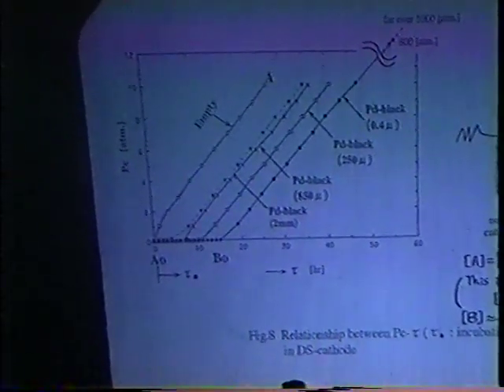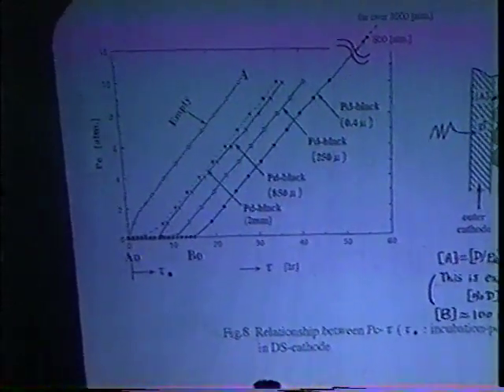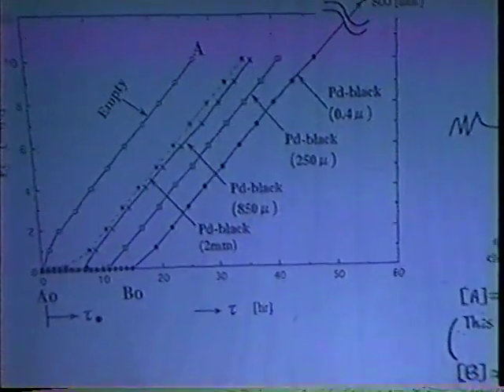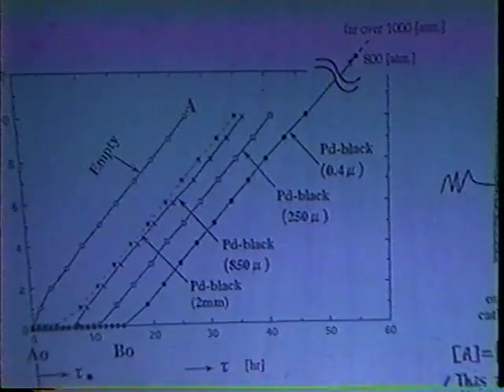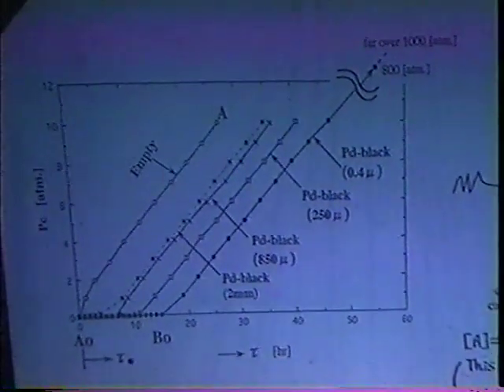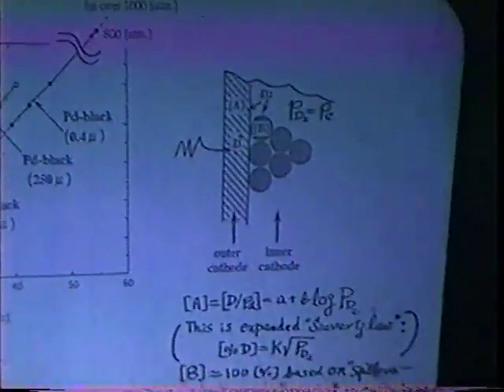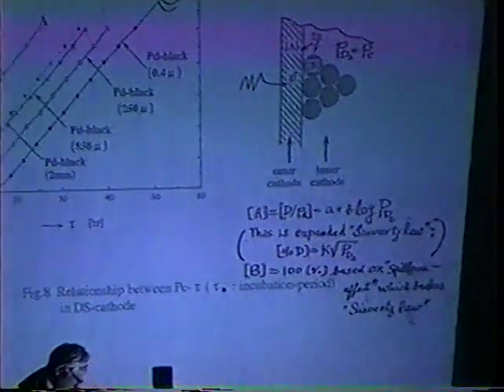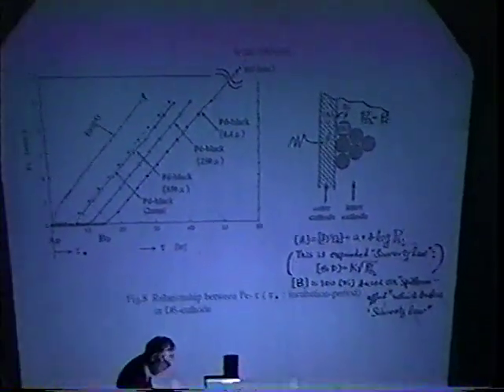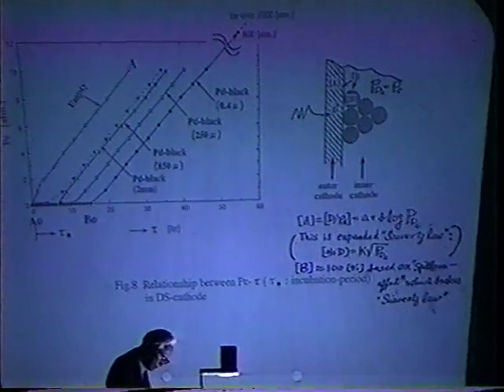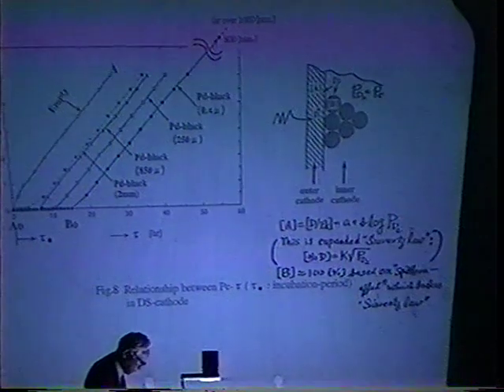In the right side diagram, the deuterium concentration inside outer cathode A and inner cathode, palladium black B, are significantly different. A is controlled by Sieverts' law. B is controlled by the spillover effect, which breaks Sieverts' law. The reason is that when A is 90%, the inner deuterium pressure is required to be over 100,000 atmospheres. On the contrary, B is almost 100% instantaneously if within 100 angstrom in size, such as a so-called atom cluster. By the way, in our palladium black, the inner deuterium pressure may be some thousand atmospheres.